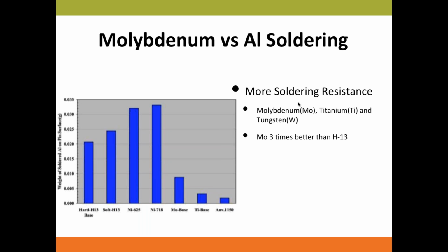Also, when you put molybdenum into the steel, the soldering resistance of the steel should also increase, because, again, molybdenum, titanium, and tungsten are refractory-based materials, and they don't like to combine with the aluminum, so the soldering resistance will increase as well.